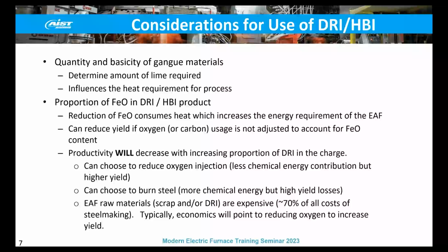If you have to add more lime—say how many pounds per ton, or kilograms per ton of slag that you produce—if you have to add more lime, you make more slag. And if it's 35% FeO, having more slag means you lose more yield, and you use more energy to do that. So there are disadvantages.